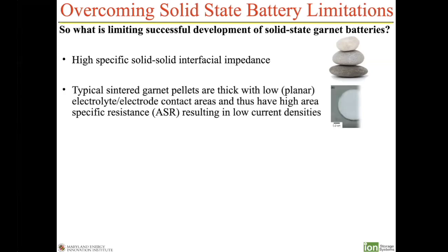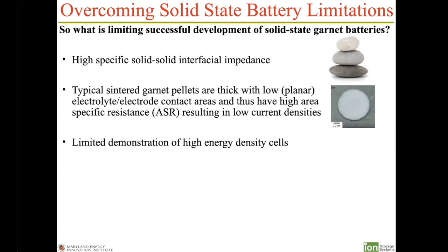The other is typically these things are pressed and sintered disks, which are then polished, and you can see a photograph of one to the right, and you have a planar interface. And because it's thick, the ohmic ASR is very large, and because it's planar, the interfacial area with the electrodes is very, very small. Both of those result in a very high impedance with typical garnet electrolytes. And as a result of those two things, there's been limited demonstration of high energy density cells.